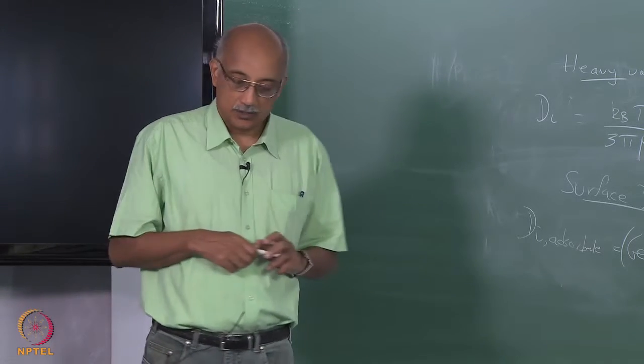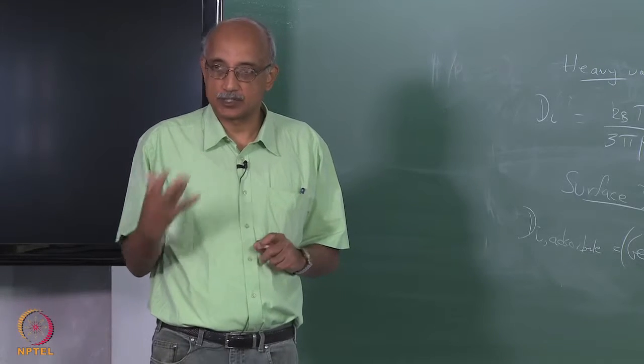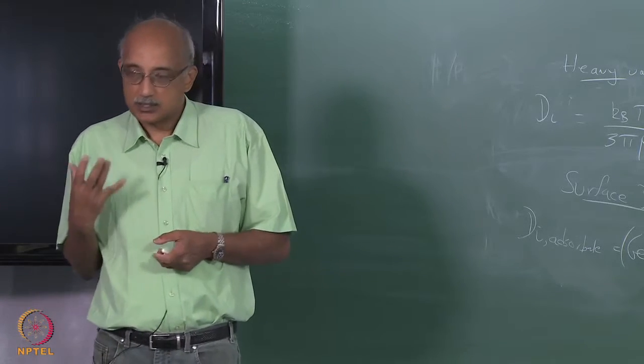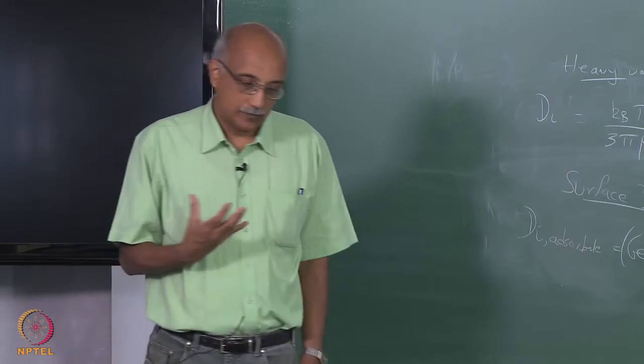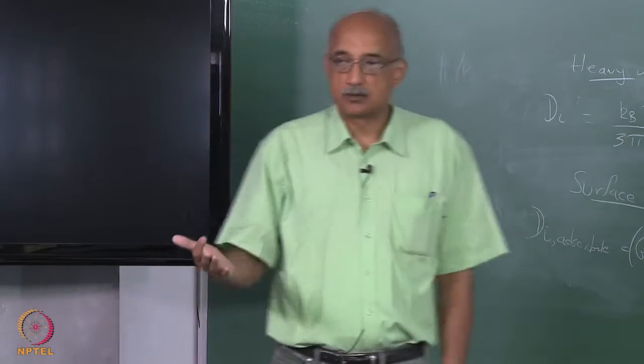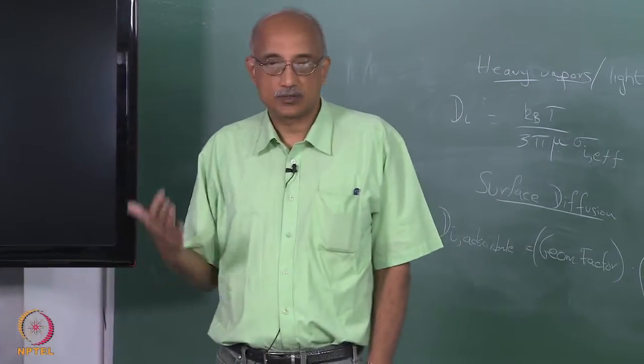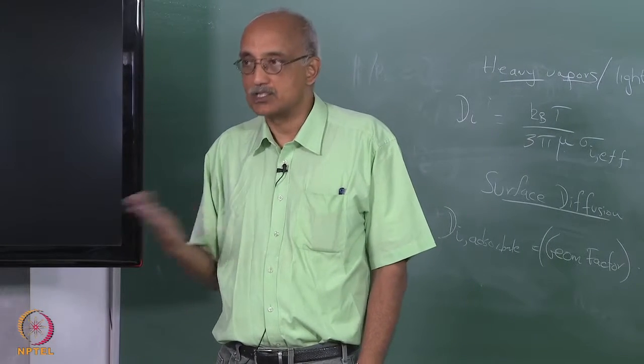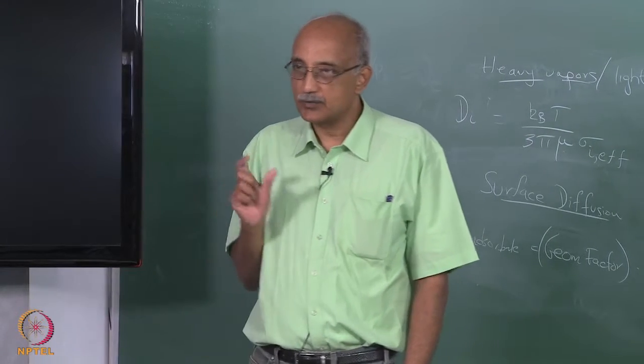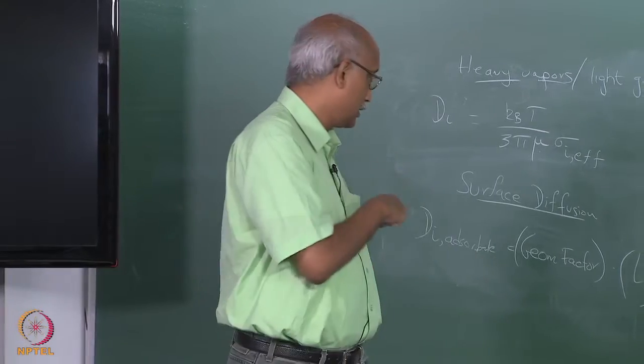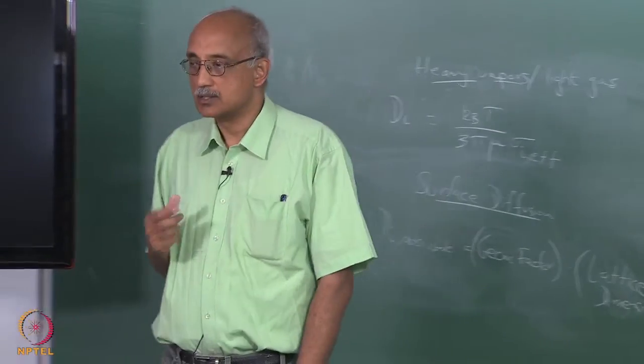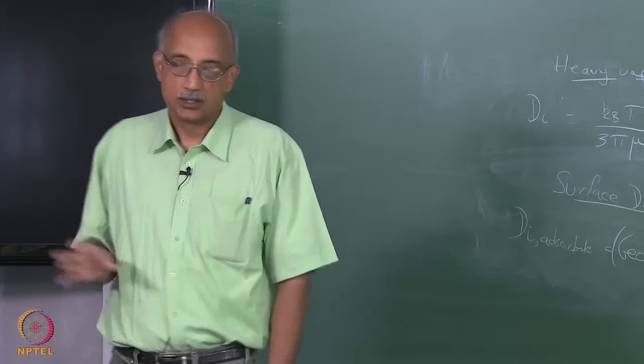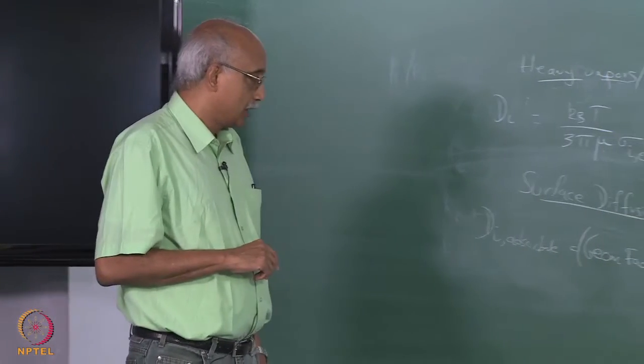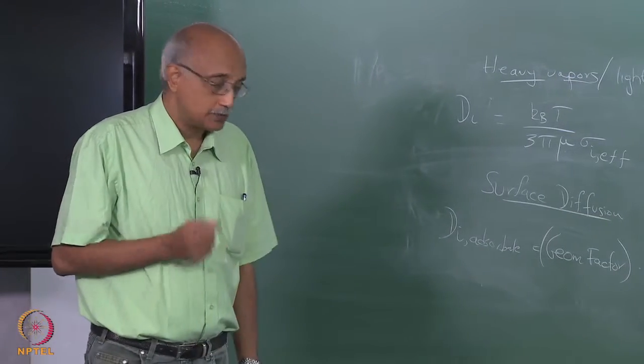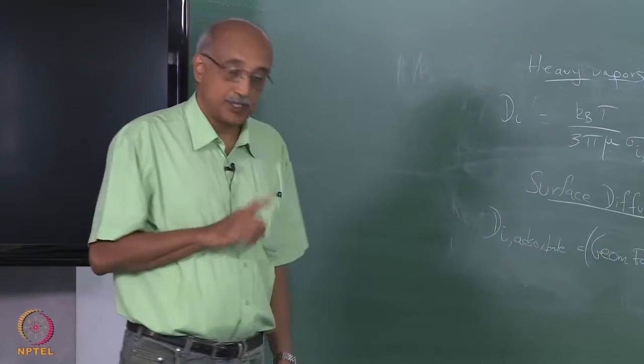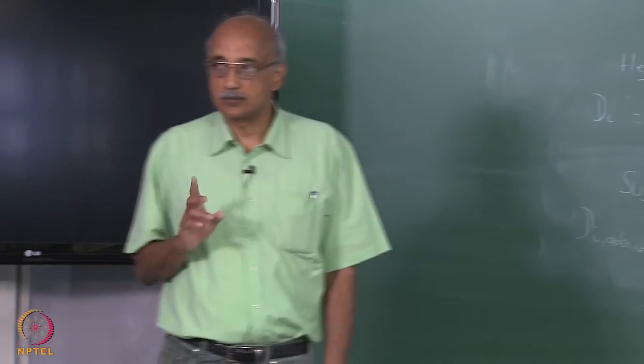The lattice dimension reflects the crystallinity of the substrate. A crystalline structure is one where the energy required to go from one interfacial site to the next can be quite high, the energy barrier. So, the degree of crystallinity which is reflected in a lattice dimension is another key parameter in determining the rate of diffusion. Of course, the attempted jump frequency, now that is a temperature dependent parameter.